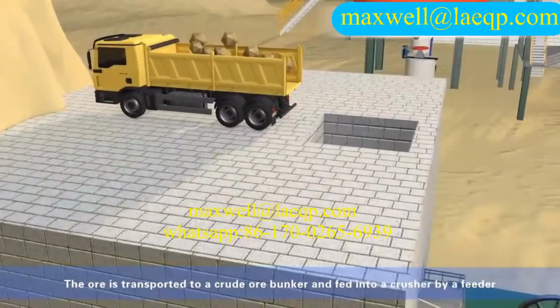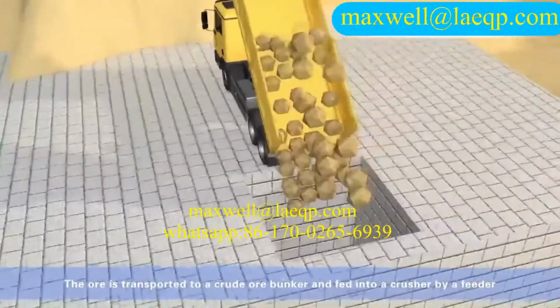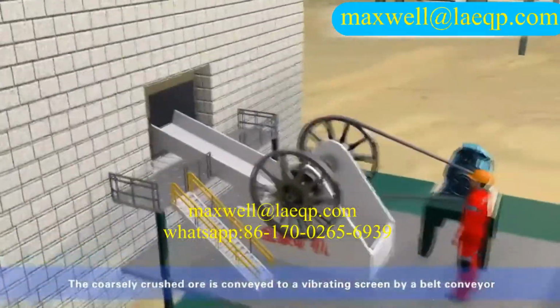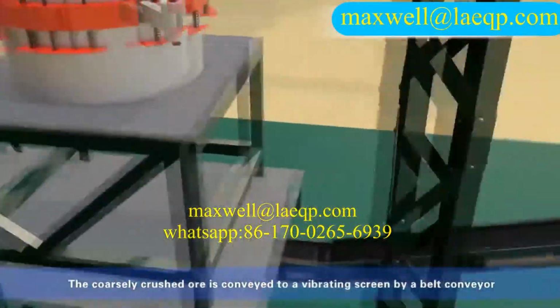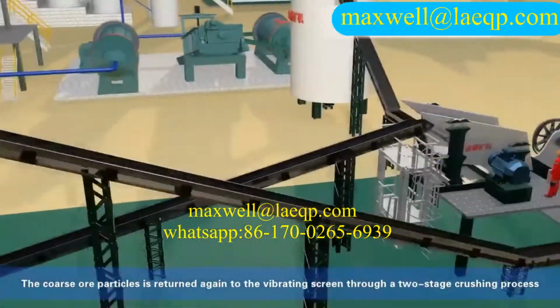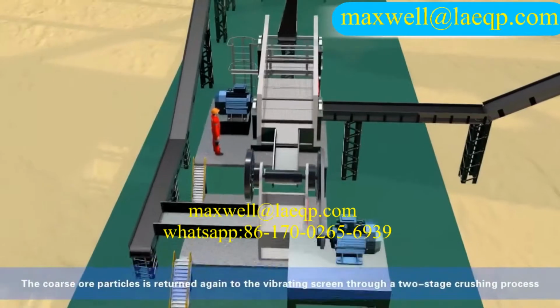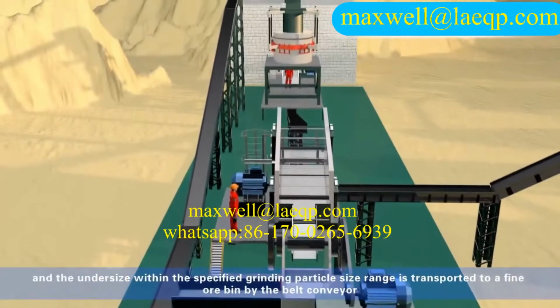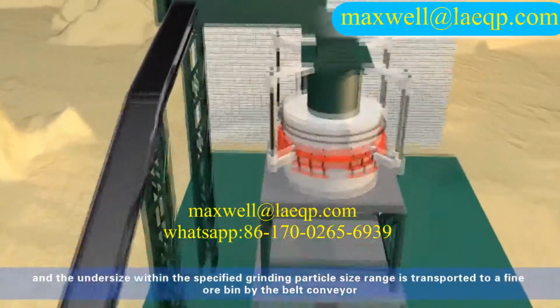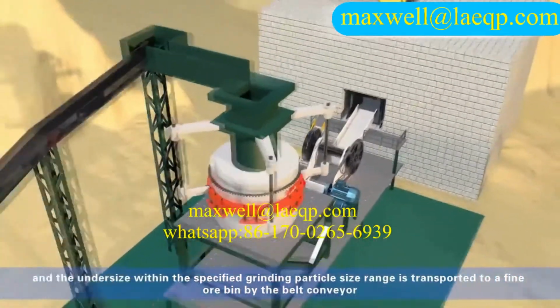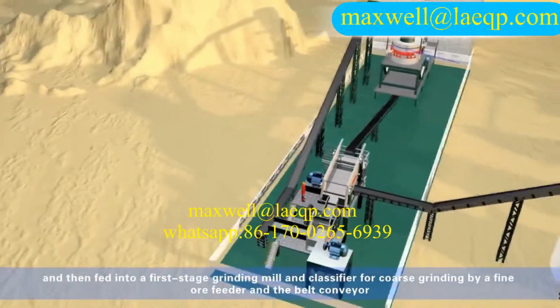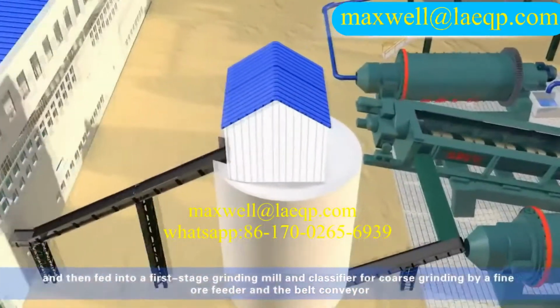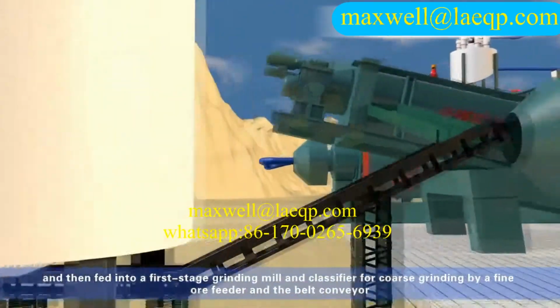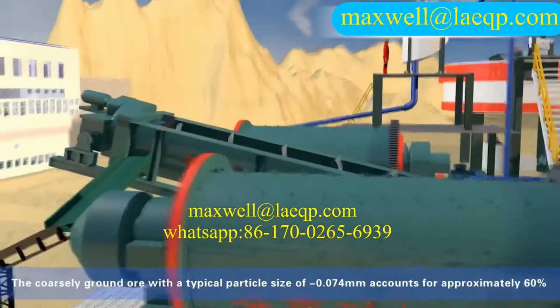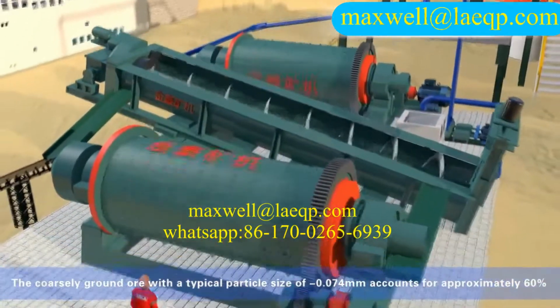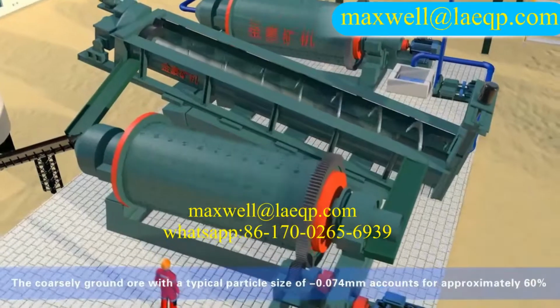The ore is transported to a crude ore bunker and fed into a crusher by a feeder. The coarsely crushed ore is conveyed to a vibrating screen by a belt conveyor. The coarse ore particles are returned again to the vibrating screen through a two-stage crushing process. And the undersize within the specified grinding particle size range is transported to a fine ore bin by the belt conveyor, and then fed into a first-stage grinding mill and classifier for coarse grinding by a fine ore feeder and the belt conveyor. The coarsely ground ore with the typical particle size of 0.074 millimeters accounts for approximately 60%.